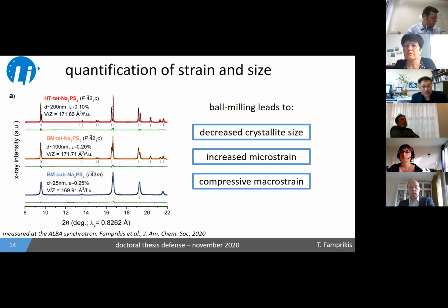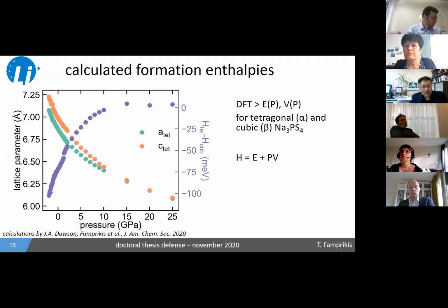So we got the idea that maybe we can explain why mechanochemistry stabilizes the cubic structure by doing some DFT calculations as a function of pressure. So this is what I'm showing here. Basically, we scan at different pressure values and calculate the energy and the volume for the tetragonal and the cubic polymorphs of Na3PS4. What we can see right away on the left is the lattice parameters of the tetragonal polymorph, which have the expectable difference at zero pressure. But as we increase pressure, they converge. When a equals c, we basically have a cube.